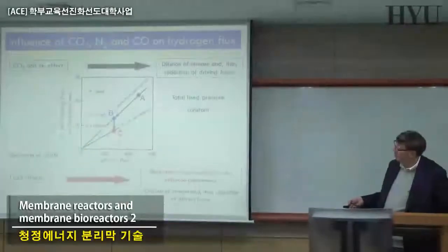That's why you realize that something's happening, because there is a strong term here that is just decreasing the available surface where the hydrogen can be split, dissociated. So that's an important phenomenon that takes place in this case, and this was relatively new, as you see here in the reference, because it was not known before.